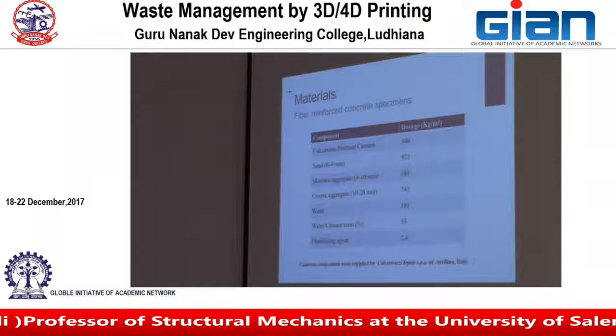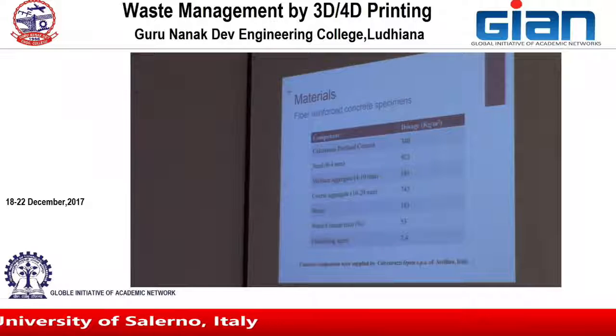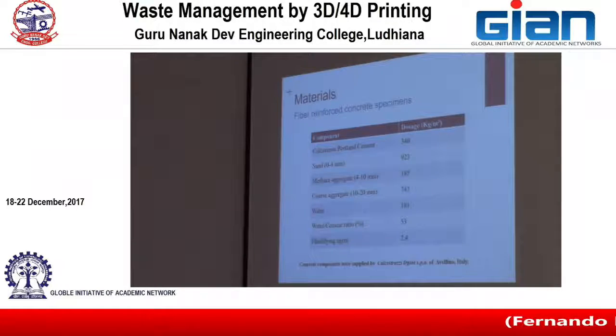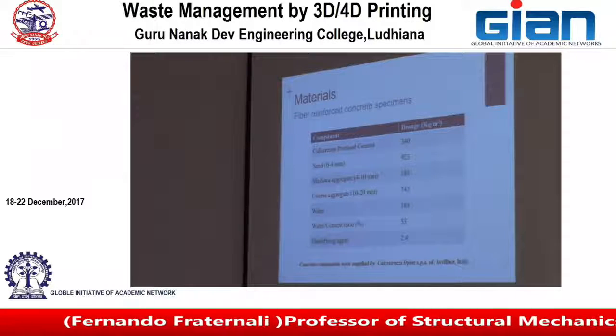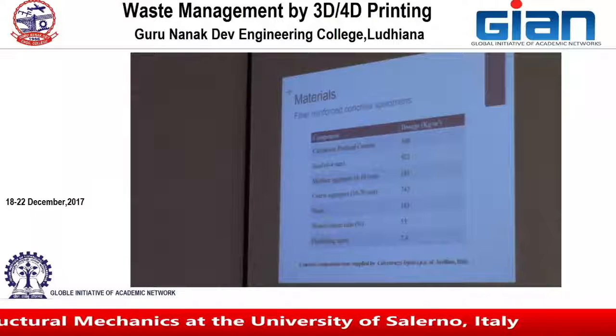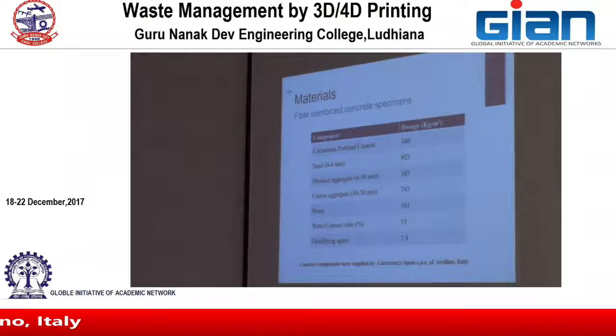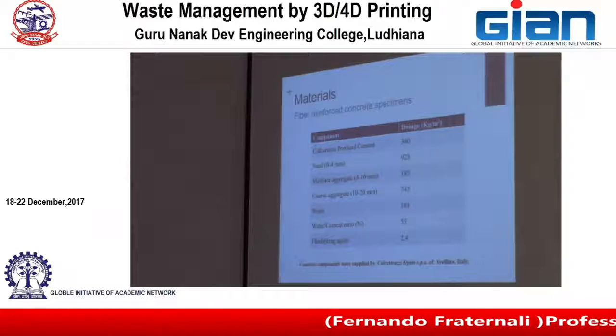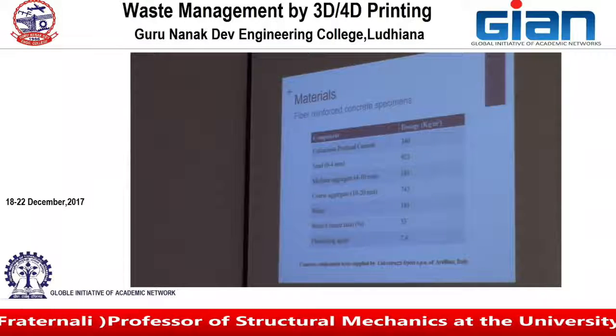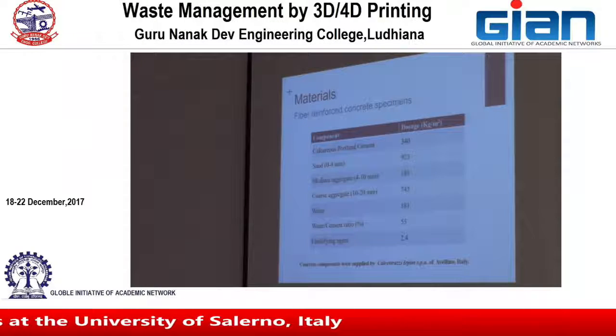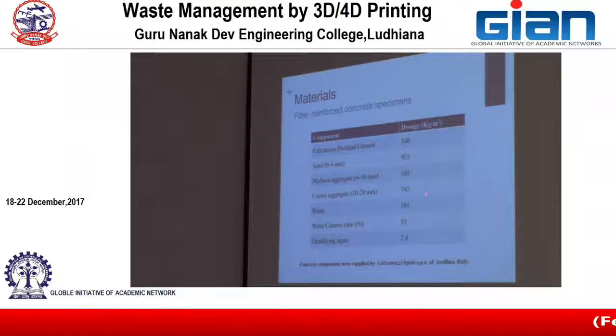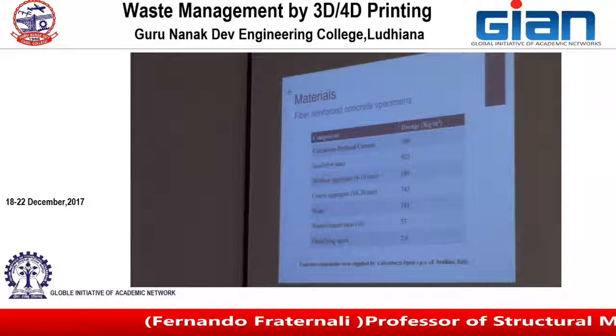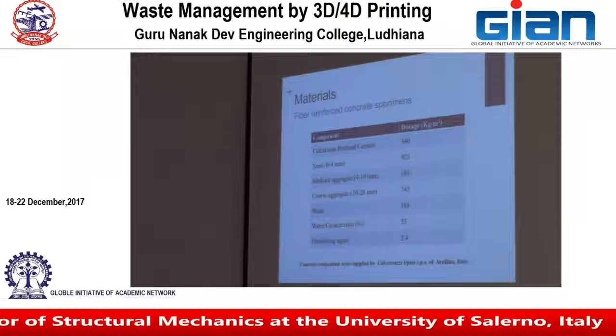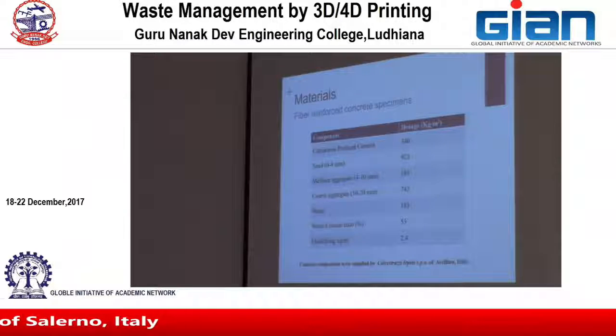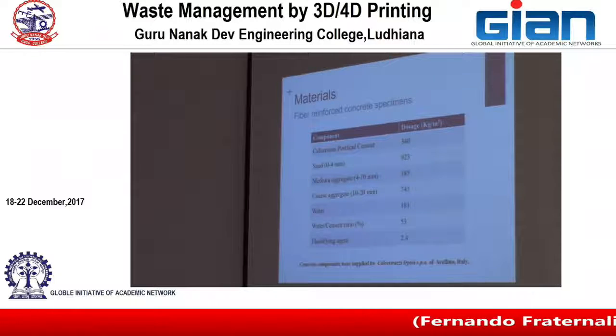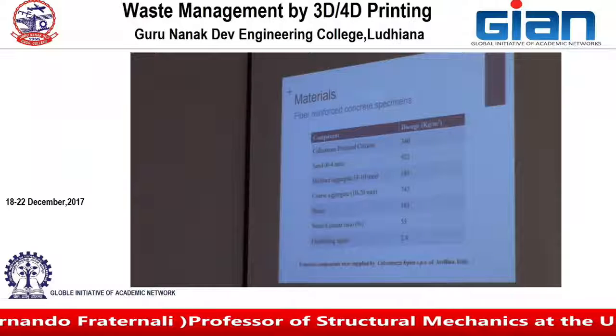There are people expert in cementitious materials, I don't know if they are here today. Anyway, we used this concrete with a water to cement ratio of 0.53, and also a fluidifying agent to increase the workability. This is a ratio that we have to consider in order to mix concrete with plastic fibers: a quite high water to cement ratio is needed for that reason. And this is the mix design of the concrete that was analyzed. It was a Portland cement-based concrete.